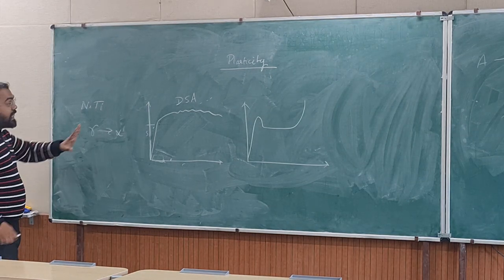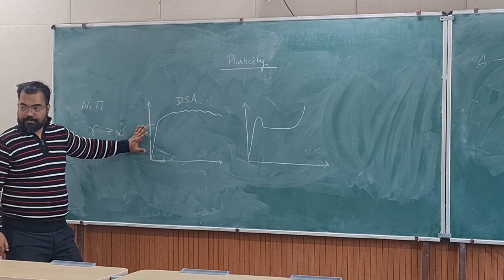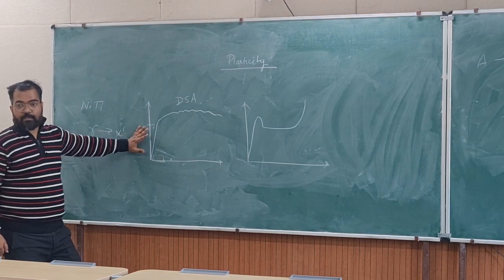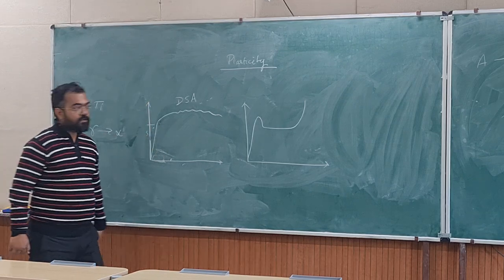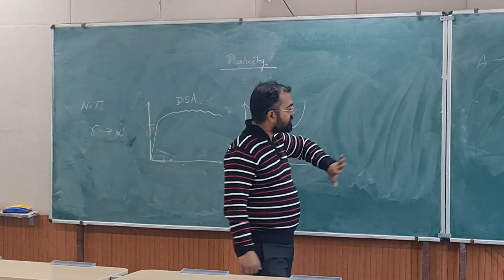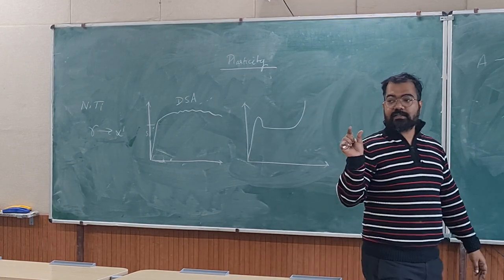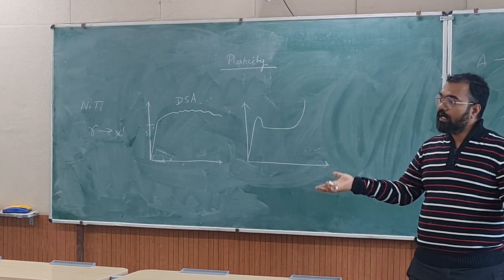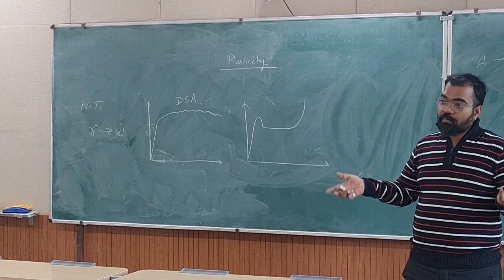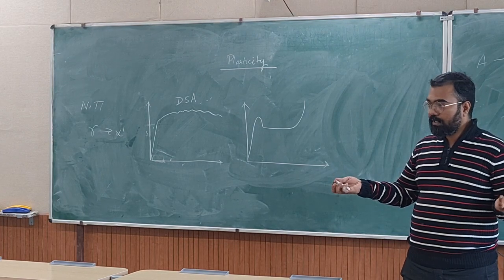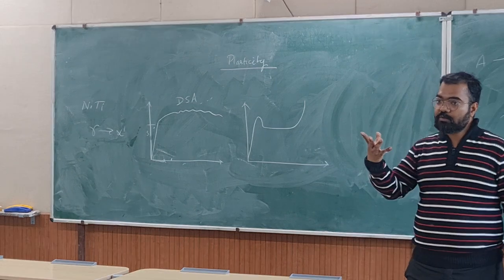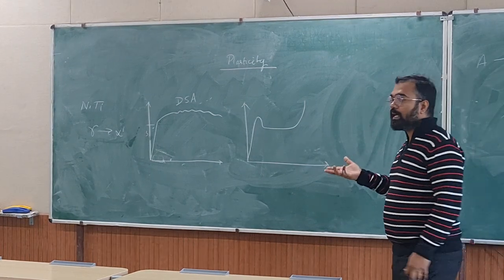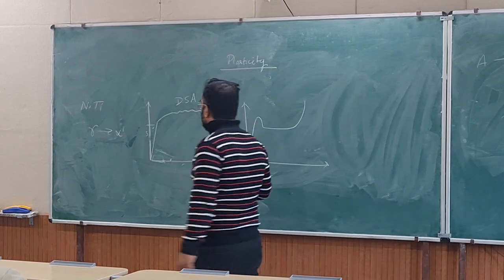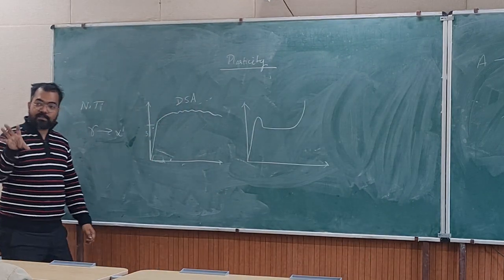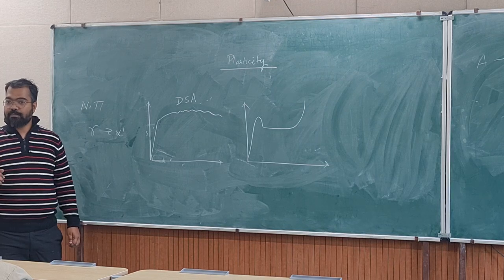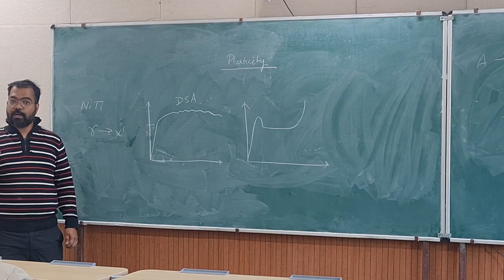That phenomenon can also happen in steel. When we apply stress, and in our system we have retained austenite. I have wiped out that diagram. But some of the austenite couldn't transform to ferrite, it remained at room temperature. But it is not stable, it doesn't belong at room temperature. It's a phase which belongs to a higher temperature, so at room temperature it has been trapped. When you apply stress, it gets sufficient energy to transform, and that is called deformed martensite.